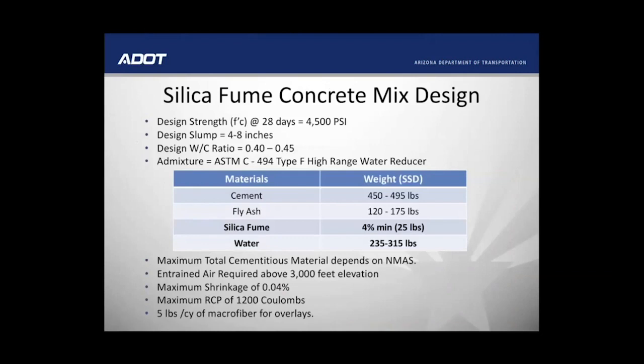So here are the general requirements for a silica fume concrete mixture that would be placed on one of ADOT's bridge decks. The mixture is somewhat prescribed but gives the suppliers room to develop a suitable mix with the materials they have available. Much of this will be governed by the aggregate source, the nominal maximum aggregate size, and the initial water demand to create a viable mix that can then be adjusted with water-reducing admixtures to get the desired workability. Notice the total cementitious material is limited based on aggregate size. The smaller the aggregate, the greater the water demand, which requires additional cement to maintain the water-cement ratio and strength, which increases paste content, which is where shrinkage occurs. We limit shrinkage to 0.04%.